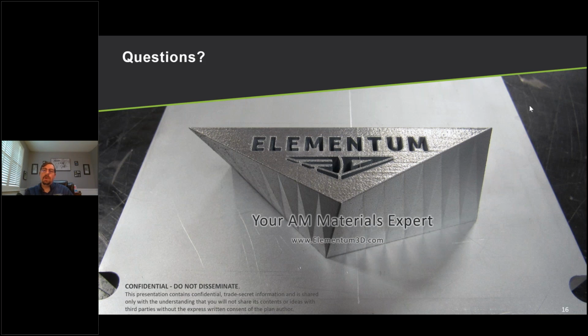Fatigue is a question. So we have seen some fatigue improvements. I'll start with, because we have more data in the aluminum alloys, we've seen some really interesting results with fatigue improvements in that system, in that we're seeing almost a pseudo fatigue limit in aluminums, which is not typical. We're also seeing better fatigue numbers as well, and it's almost as if the crack resistance has improved because of those particulates, and because those particulates are so small, they don't act as a crack initiator either. So we have seen some benefits in the nickel superalloys as well.